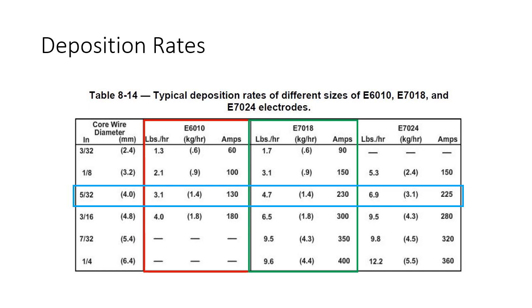I know I'm not intending to talk about E7024, but you can see where E7024, which is for flat and horizontal fillets, you can really get some deposition rates. Your deposition rates with that are two and a half times what you'd get with E6010. But the 7018 has up to 40% of that flux coating as iron powder, so that's going to help our deposition rates. This is one of the things we need to keep in consideration when we're trying to decide what our intended goal is. So if you're trying to fill up a very big hole with filler metal, E6010 is probably not your choice if you're going to try and do it in an economical fashion. But like I said, I wanted to show you the different deposition rates and that there is a difference between 6010 and 7018.